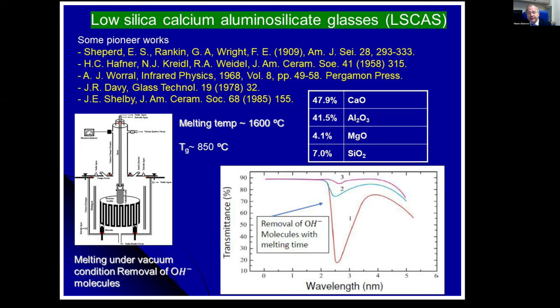And also we work in a system making the melting in vacuum. It's not high vacuum, but it's 10 to the minus 3 to remove water. And also all the environment inside the furnace is made of graphite, like the resistance and the crucible. All the components are graphite, and all the process of making the glass, including the quenching, is done inside the furnace. There is no contact with air during the process of preparing the sample. So this glass has a transition temperature of around 850 Celsius, and the melting temperature is 1600 degrees.